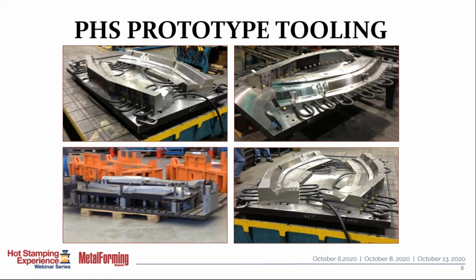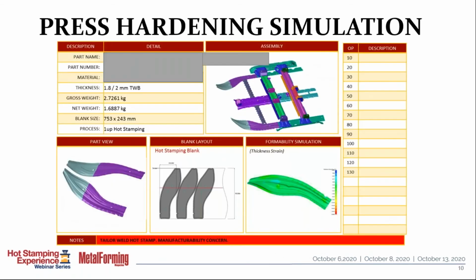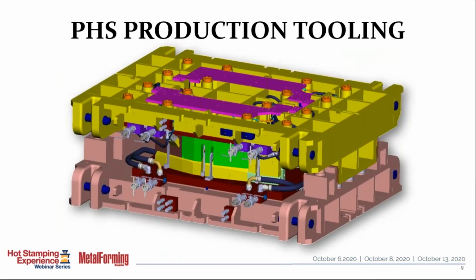Most of the time, what we're trying to do with water cooling is to cool off the die to improve cycle rate. If we didn't do that, we'd have to wait for a while between unloading the part and loading the blank to allow the die to cool off. So the reason we do some simple cooling on prototypes is simply for cases where we're going to make quite a few prototype parts and we don't want to spend the extra press time. In the production tool, it's much more complicated. The production tools have cooling channels that are developed to efficiently reduce or remove the heat so that we can improve production rate.